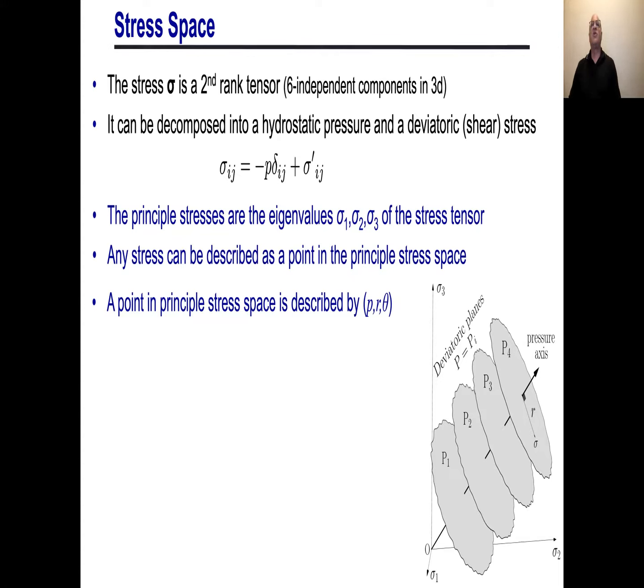Okay, so if I have a general stress tensor sigma ij, I can find eigenvalues. That gives me sigma 1, sigma 2, and sigma 3. It's a second rank 3x3 tensor. So there are 3 eigenvalues and 3 eigenvectors corresponding to orientations. So any stress state that I choose to apply, I can describe as a point in this stress space, okay? So this is sigma 1, sigma 2, sigma 3. The diagonal line here is the pressure axis. So as I go along this line, I'm increasing pressure. Any plane that's perpendicular to the line has exactly the same pressure.